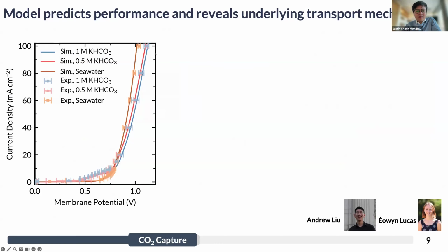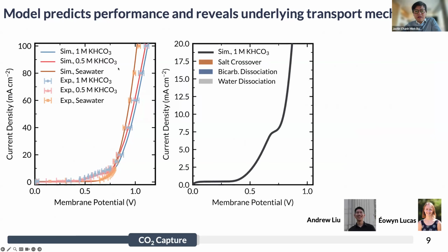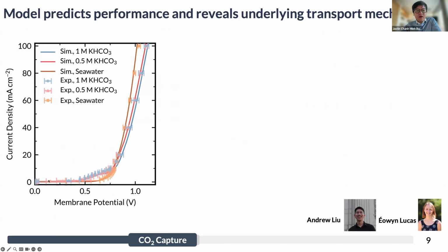So Éowyn had been testing these bipolar membrane systems for oceanic carbon capture and also for operation of these electrochemical calcination processes with seawater and also varying concentrations of carbonate. And what we were able to do was see how the current voltage characteristics of the bipolar membranes that she measured in these different carbon capture solutions compared to what our simulations predicted.